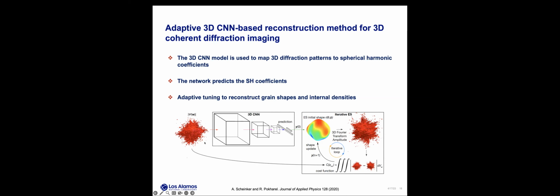And then we train our network, and once trained, given a 3D diffraction pattern, it predicts the spherical harmonics coefficients. And then we go one more step where we iteratively tweak these spherical harmonics coefficients to further optimize, using a method called extremum seeking to adjust the shape to get a better match between our measured and predicted diffraction patterns.